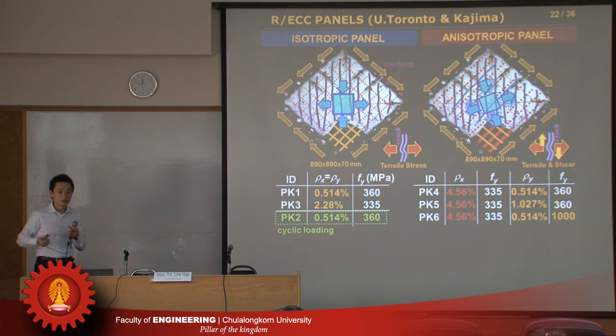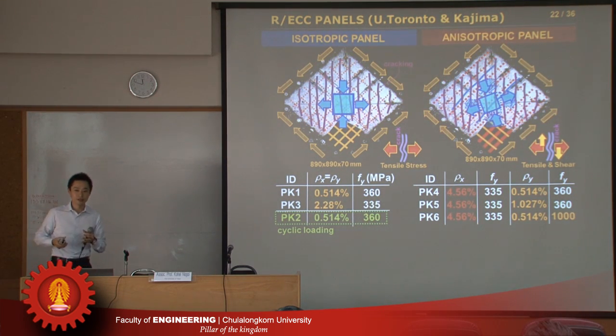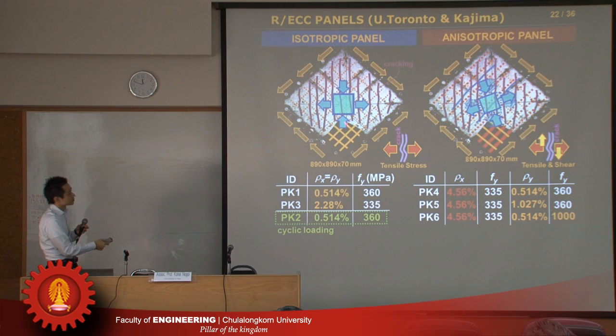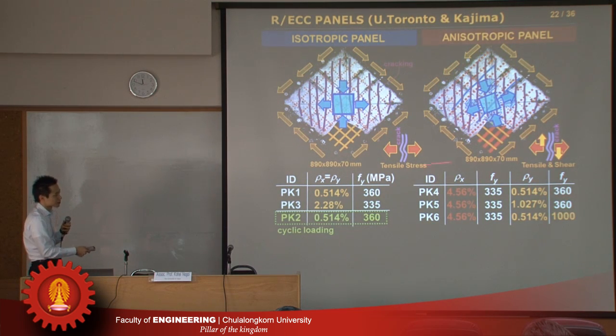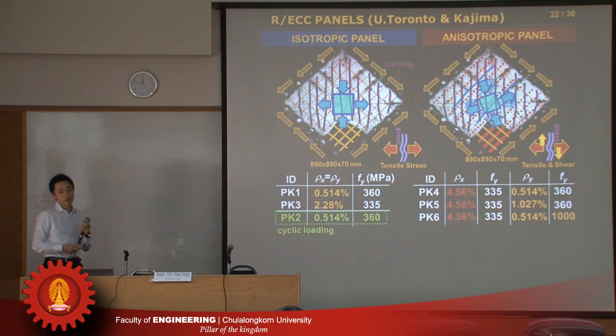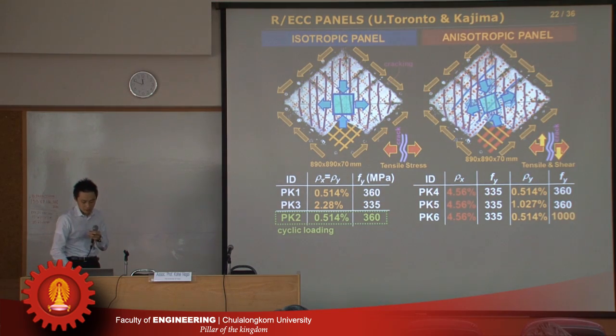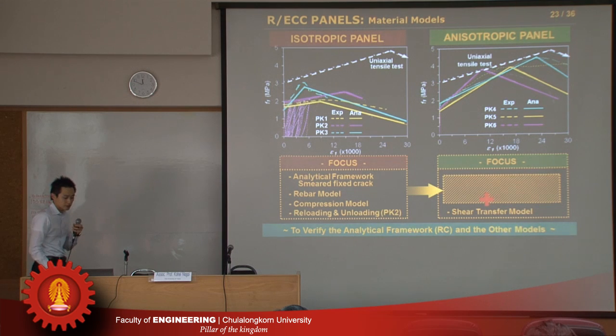And Toronto University has very well managed shear panel test equipment, where specimens with the same reinforcement in both directions and different reinforcement in the X and Y directions were prepared. Totally 6 tests were done. So this is a case with the same reinforcement ratio, and this is a case with a different reinforcement ratio. What happens in the case of a different ratio is that after the cracking, because of the different reinforcement ratio, anisotropic phenomena occur after the cracking. So this is a very complex situation. Then we try to simulate these phenomena.